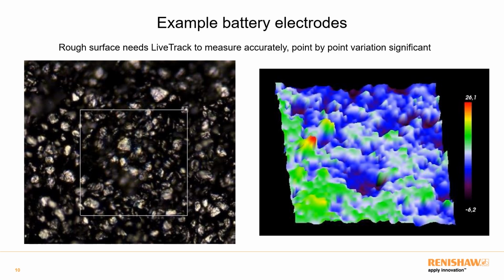But in the case of LiveTrack, we don't need to worry about it. What happens is, again, we move the sample up and down to correct for this change in focus in real time. What you can see from the optical image here, and I'll just circle a region, is a region which is out of focus. And you can see this region on the corresponding LiveTrack image here. So we can see the two dips, again, giving us confidence that this is all working fine as expected. Looking at this sample, we can see that the change in height is around 30 microns. So again, this is bigger than the depth of field of the sort of objective lenses you'd like to use for these experiments. And on the next slide, I'm going to go into a bit more about the science of this sample.